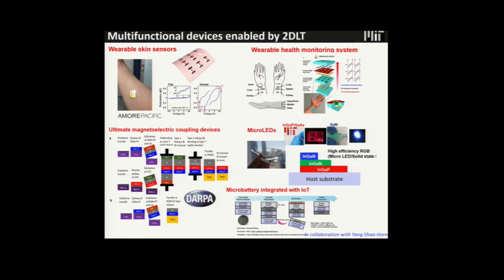But if we use the 2D-LT technique, we can grow high quantum efficiency LEDs on an ideal substrate. They can peel off, and we can stack them up. So this program is also going on. And this program is also very interesting because 2D-LT works so well for oxide, functional oxide material, because of strong ionicity.